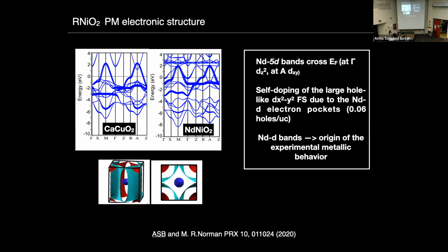So what you see on the left is just a prototypical cuprate band structure in which we have just a single dx²-y² band crossing the Fermi level. That is just our horizontal line there. In the nickelate case, you see that the situation is kind of similar. You keep on having that band, but you instantly see that there is something also quite different, in that you have these extra bands crossing that I marked here in red. And those are neodymium 5d bands.